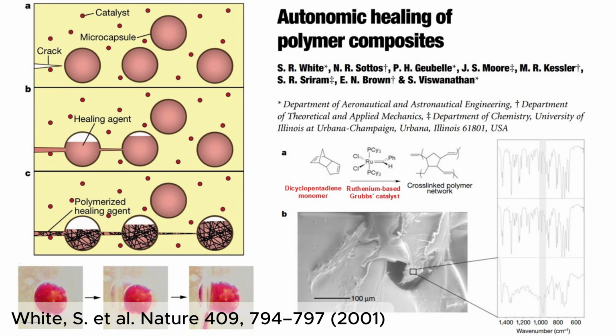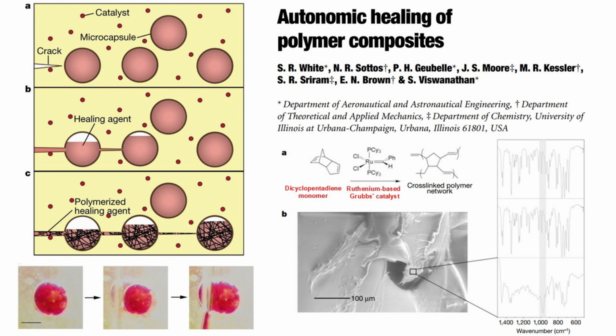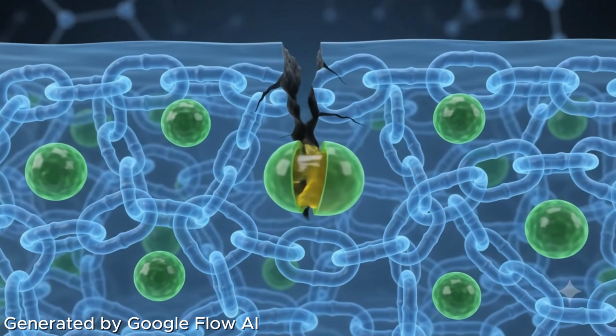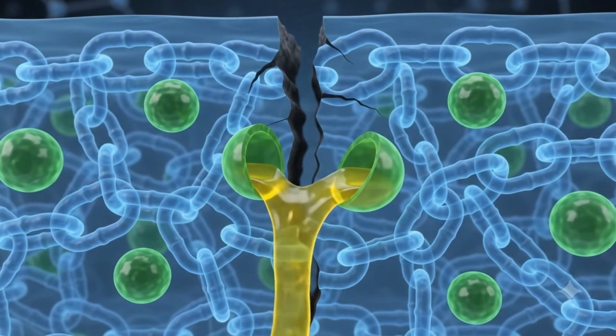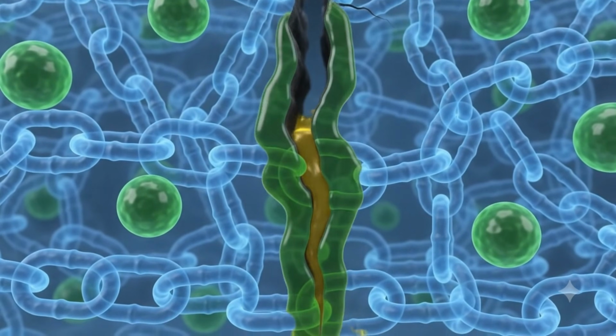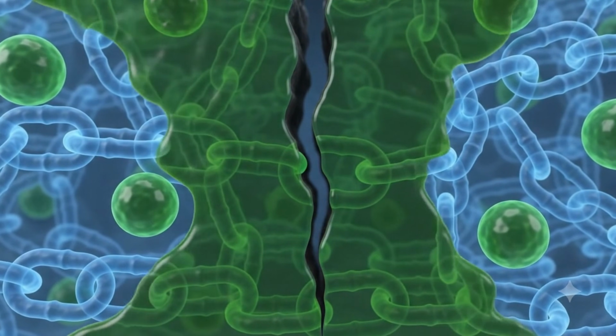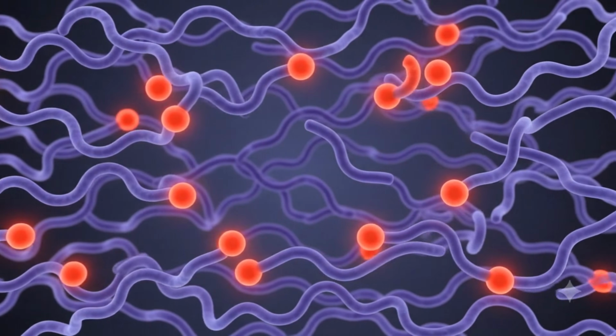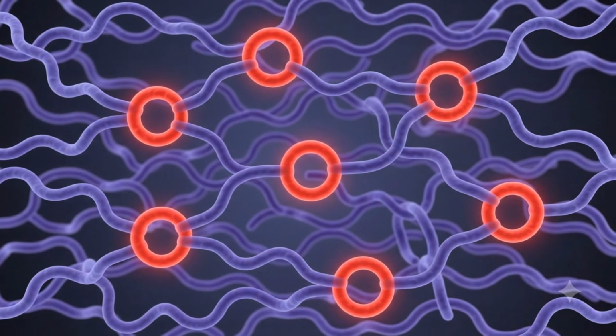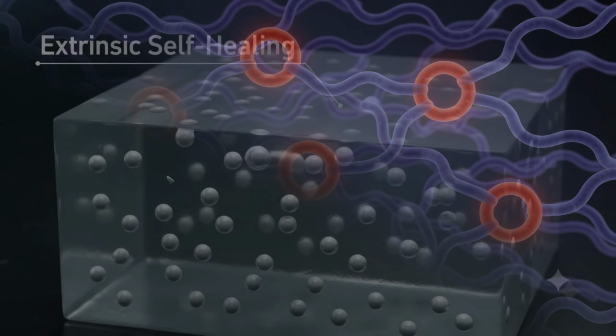For decades, self-healing polymers relied mainly on chain diffusion and usually required heating. A major breakthrough came in 2001 when White and co-workers developed the first autonomic self-healing polymers capable of repairing cracks at room temperature without external intervention. The system used microcapsules filled with dicyclopentadiene monomers dispersed in a polymer matrix together with a catalyst. When a crack formed, the microcapsule ruptured and released DCPD into the damaged area. Contact with the catalyst triggered polymerization, forming a new polymer network that sealed the crack and restored strength. This became the first well-known extrinsic self-healing system, one of the two main categories of self-healing polymers.